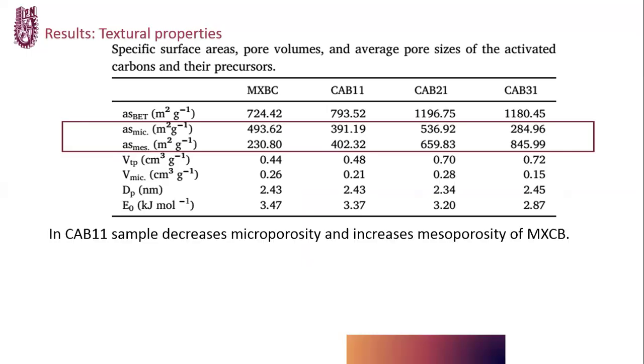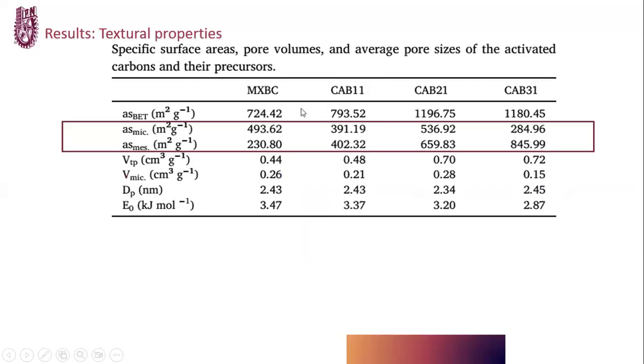In this slide, we have the comparison of the information that isotherms provide. Please note, first of all, that we are here reporting pore surface values that exceed 700 square meters per gram. Those that are made with non-flat sheets, typical of non-graphite structures, and whose interplanar spaces are between 0.2 and 2 nanometers.